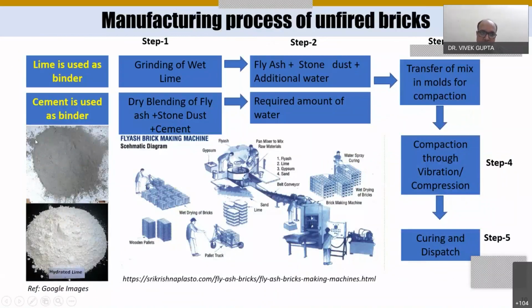We use either lime as a binder or cement as a binder, and generally we take the lime from the industry and produce the slaked lime in situ at the industry. So in the laboratory, we generally use a roller which has two drums in the pan mixer. The first step is the grinding of the wet lime. Once the lime is ground properly, then in the second step we add the fly ash, stone dust, and some additional water.